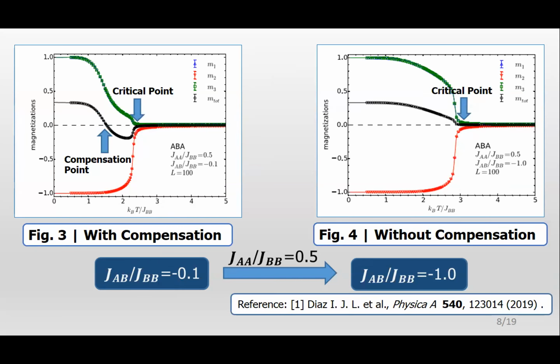Let's see, when there is no field in the system, how the system behaves as we change the temperature of the bulk. So we have two distinct scenarios. In figure 3, with the black curve, which is actually the total magnetization of the bulk, we find 2 points along the temperature axis where there are jumps from zero magnetization. The farthest one is basically the traditional critical point for a magnetic system, but the one on the lower end is the compensation point. Here the ferromagnetic coupling ratio is fixed at 0.5, whereas the antiferromagnetic coupling ratio is fixed at minus 0.1.